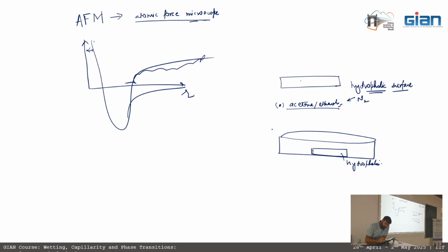And then we replace this liquid with water at atmosphere that already has nitrogen dissolved in it. So what this leads to is that as the acetone is replaced by water, it cannot take in more gas, so these bubbles start to form here.